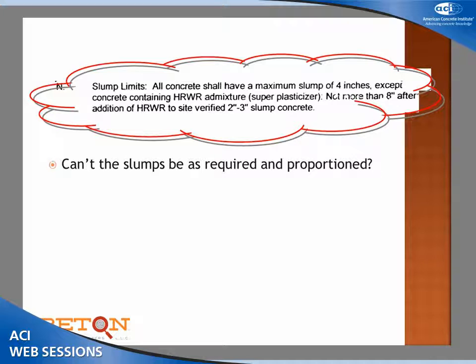So why can't you just say the slump should be what's required? In fact, when I write specifications, which I do from time to time, and I have my druthers and start with a blank page, I say the slump shall be suitable for the intended construction method without segregation, which I define because I can't remember the ASTM number, but there's a nice one for shrinkage or for self-consolidating concrete, and so I say visual stability index as measured by this method of 1 or less, which you can do on a regular slump cone. At a 10-inch slump, you will have a pretty good VSI. If it's not segregating, if you haven't interfered with the water to cement ratio, you're fine. If you have, you can get by with strength.